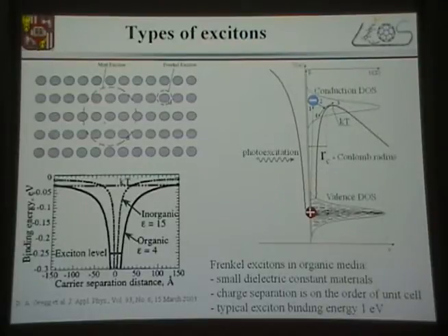organic materials have a low dielectric constant, it's around 4. Whereas inorganic are around 12 to 15, like silicon, and this results in two different types of excitons: Mott-Wannier exciton in silicon, and Frenkel exciton, strongly Coulombically bound exciton in organic materials, and that's the whole problem.